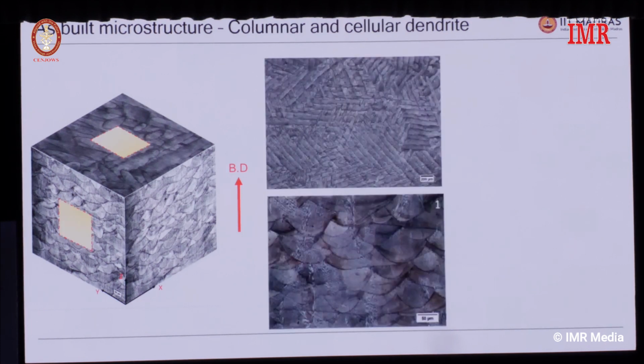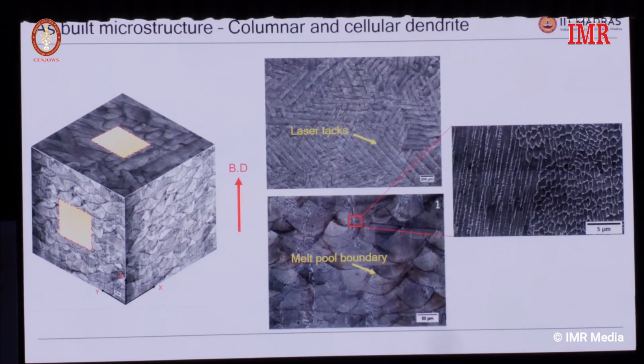Most of the metal additive manufacturing has actually started with Inconel 718, and Agnicol has been doing a lot of work on Inconel 718, but challenges remain. For example, here I am showing along the build direction and normal to the build direction. If you see, the microstructure looks very different, right? In the case of normal to the build direction, you have the laser tracks coming from the melting, and along the build direction you have the melt pools. If you go a little deeper into the microstructure, you have columnar and cellular dendritic phases.